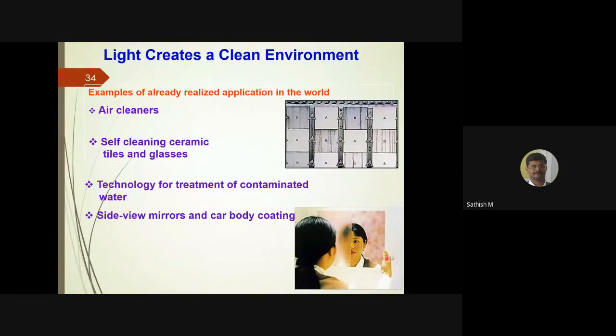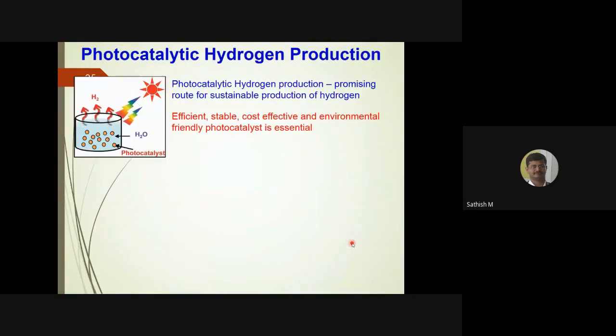Similarly, even for mirrors with super hydrophilic coating, the water adsorbed on the TiO2 coated area will be removed. You could see these clear pictures. So this is not new. Even our face creams have TiO2. So how do we use TiO2 or TiO2 based systems for our current need, that is hydrogen production? Unfortunately, though TiO2 is a well-known catalyst for photocatalytic applications, its hydrogen production efficiency is very poor.